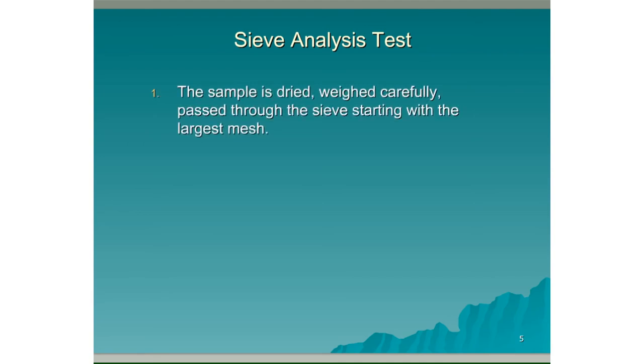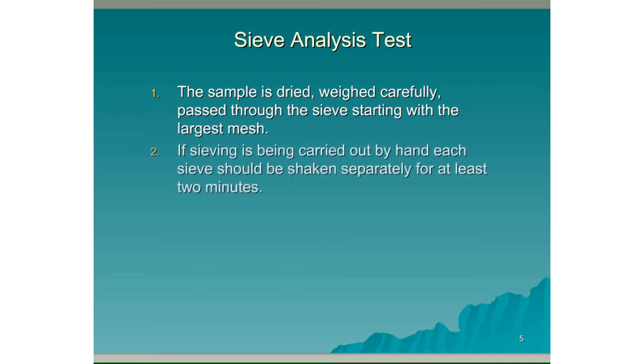The sample is dried, weighed carefully, and passed through the sieve starting with the largest mesh first. If sieving is being carried out by hand, each sieve should be shaken separately for at least 2 minutes.